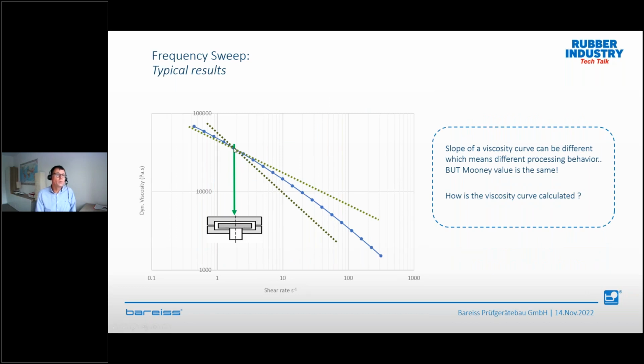Because when you're measuring a Mooney, the slope of this viscosity curve can be completely different. You have no information about this. And the slope of this viscosity curve has a huge impact on the processability of your rubber compound. That is the reason why Mooney is so limited in information.